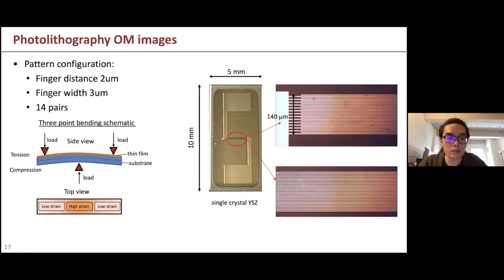And the second thing is, since this is an example of using single crystal YSZ, this won't be a problem if we're measuring a thin film, but if we're measuring bulk material, we also have to care about how deep the current goes. If the distance between your fingers is too large, then the current can go deeper. And as I just mentioned above, the strain across the sample in the Z direction is also not uniform. In that case, you will also have the signal under different strain. That's why I have to have very thin fingers and make them very, very close.